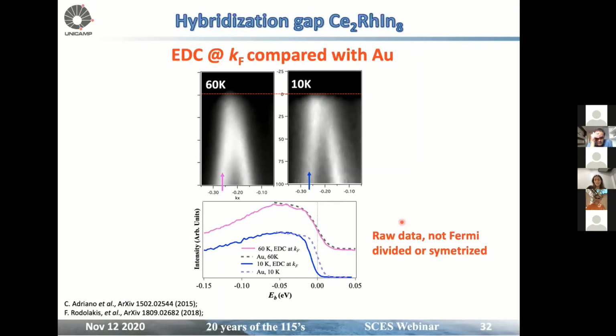But then we have the gold, we set exactly the energy we had, and we also got it at the same temperature. So we had the setup at Professor Campos' chamber, in which we had gold and then sample. So we measure gold, we move the sample, and then we measure the sample. So it's the same experimental situation. And here I point out that I'm using raw data, not Fermi divided or symmetrized ones. So if we compare 60 Kelvin data from the sample with gold, we see no gap. And if we compare 10K data with gold, we see a shift of the spectral function.